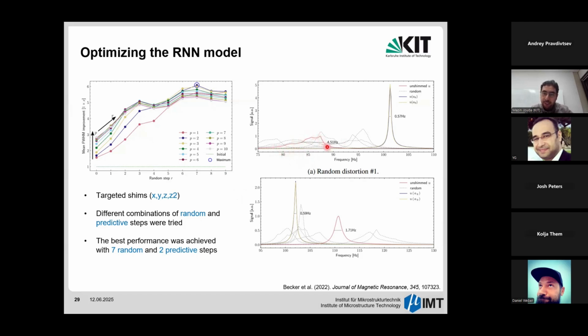We start from this red spectrum, which is the distorted or unshimmed spectrum. And the model starts making 7 random steps. So these are the dotted lines. These are the spectra corresponding to those 7 random shim predictions. And after that, the model starts doing predictions. So it does 2 prediction steps. And you see immediately it goes from the unshimmed to almost the optimum shimming condition.